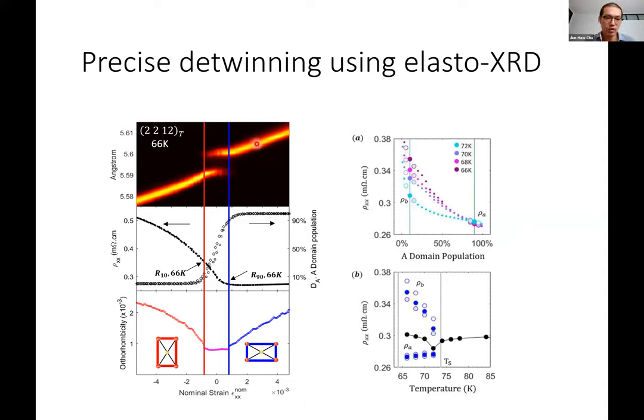So this part of the figure you have seen already, but now let's say we plot the intensity ratio of these two, and then we can plot the domain population as a function of strain, going from fully A domain this way to fully B domain the other way. And this black curve is the resistance versus strain curve.